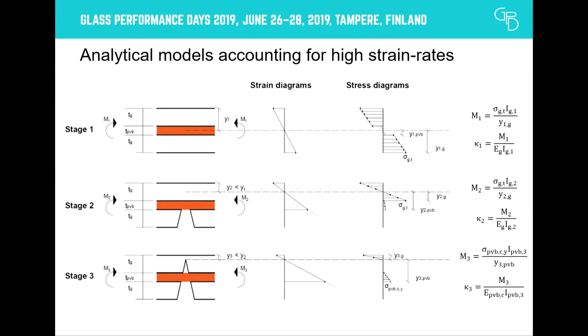In all three cases, the bending moment capacities have been derived by transforming this composite material into an equivalent glass or PVB section and calculating the moment capacities assuming plane sections remain plane. The equivalent curvature capacities have been defined assuming linear elasticity in these stages. Stage 3 is valid as long as the interlayer does not yield. Even though this does not refer to true plasticity, as PVB is a viscoelastic polymer, we refer to yielding as the observed reduction in stiffness in the material tests.